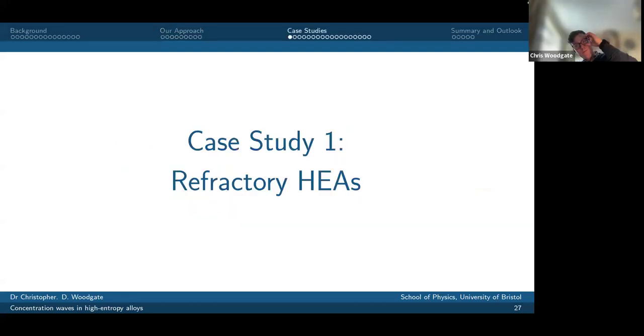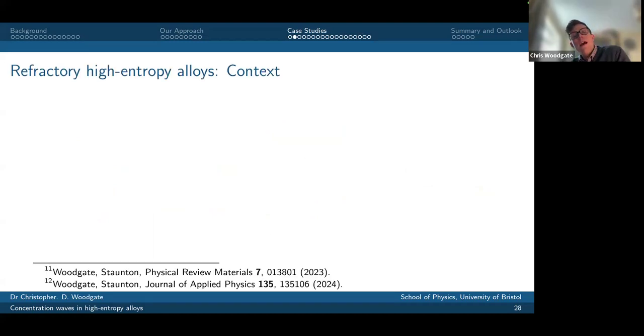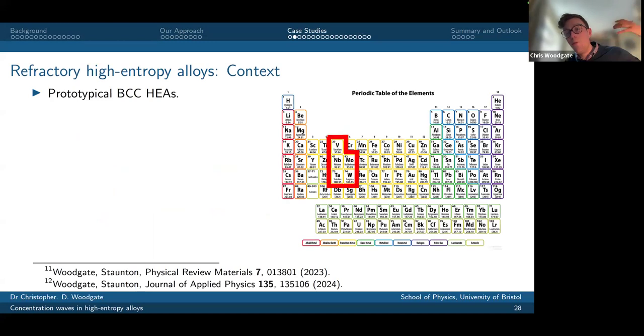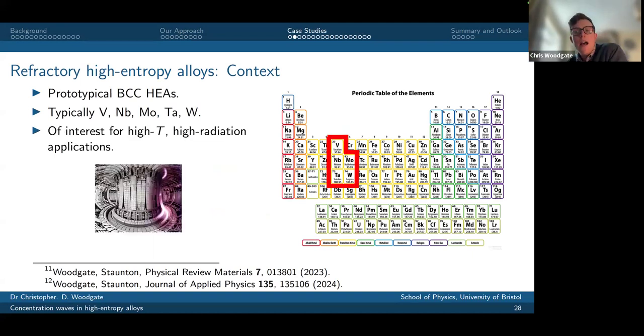Okay, so I wanted to give you a few case studies. The first case study I want to talk about is for these so-called refractory high entropy alloys. For a little bit of context, these are the prototypical body-centered cubic high entropy alloys. So we're talking about elements like vanadium, niobium, molybdenum, tantalum, tungsten. These are of interest for high temperature, high radiation applications, because all of those constituent elements have nice high melting temperatures, and on their own, they're quite good at resisting being irradiated as well. The example I want to focus on is the 4-component niobium, molybdenum, tantalum, tungsten.